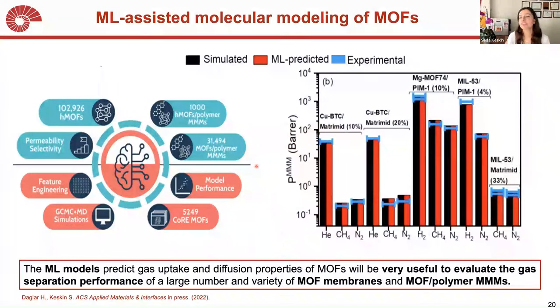And of course, reviewer two was again there, he asked us to compare the predictions with the experiments. And this time he's very right, because there are a lot of different mixed matrix membranes reported in the literature. In the morning, we just listened to some of the mixed matrix membrane studies from the conference. So we prepared this permeability figure, showing the ML predicted, simulated, and experimentally measured permeability. Sometimes you see two different experimental bars, because different research groups can make the same mixed matrix membrane and measure different permeabilities. And of course, the machine is learning from the simulation. Therefore, black and red bars are very close to each other.